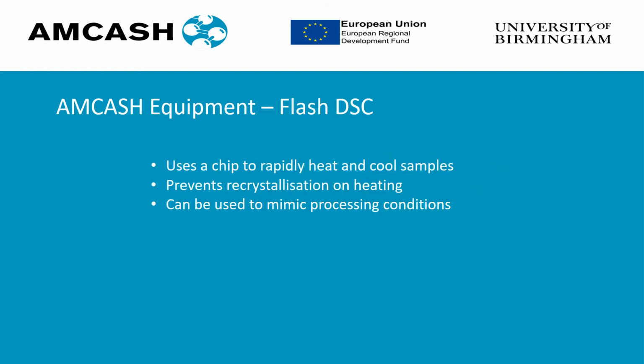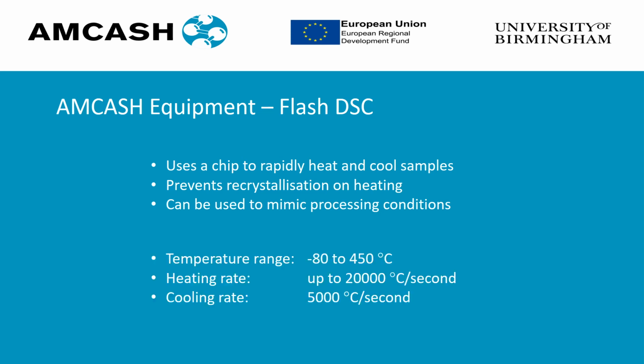We also have a flash DSC. This is used as a chip to rapidly heat and cool the samples, and this prevents recrystallization and heating, producing a more accurate result of the material present. It can also be used to mimic processing conditions. The flash DSC can operate at a temperature range between -80 degrees C and 450 degrees C, has a heating rate of up to 20,000 degrees per second and a cooling rate of about 5,000 degrees per second.